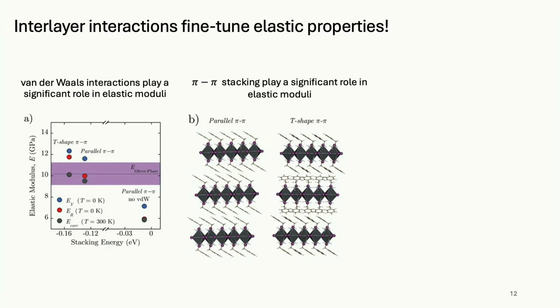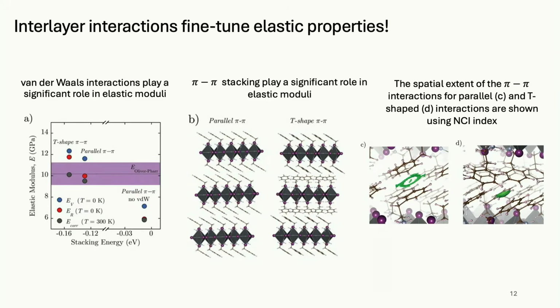But it turns out some of the molecules can swivel around relative to the others, and that T-shaped pi-pi is actually a little bit lower energy. And in fact, that drops the elastic modulus right into the region that is where it's experimentally measured. And so we think that the molecules can swivel around, become a little bit more stable, and this increases the elastic modulus slightly because they have this stronger interaction. So that kind of